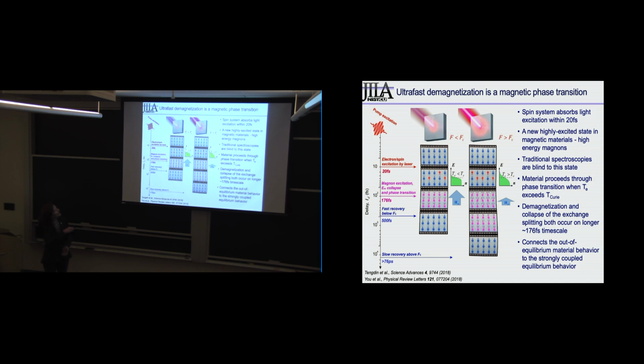And so the idea is, if you heat it gently, you heat the electrons, there are some above the Fermi level. One of these hot electrons can then undergo a transition from above the Fermi level to the minority band, because you pump some out of the minority band to below the Fermi level, and that will give you a spin flip. But if you only have a small number of spin flips, because you didn't heat very strongly, that material can recover very quickly, and you haven't really driven a magnetic phase transition.